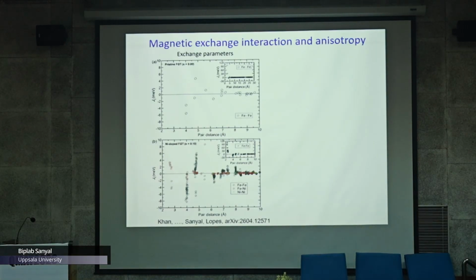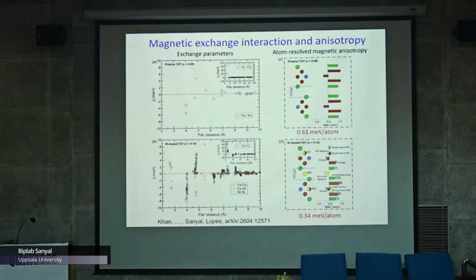So basically it follows the experimental observation, and then you can look into the magnetic anisotropy. By magnetic anisotropy, I mean the magnetocrystalline anisotropy that comes from spin-orbit coupling. We can do an atom-resolved magnetic anisotropy, and if you look into that, this is the pristine system. A plus here means out-of-plane magnetic anisotropy, and minus means in-plane magnetic anisotropy. Most of the atoms in the system, there are two layers, this is one monolayer, this is the second monolayer, are all carrying local magnetic anisotropy energies.